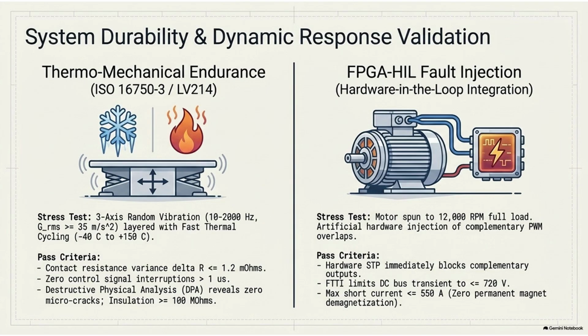While it's shaking, the table is sitting inside a thermal shock chamber. They rapidly cycle the ambient temperature from deep winter negative 40 degrees Celsius up to a scorching positive 150 degrees Celsius. Wow. And they leave it in this state, vibrating and thermally expanding while running high power through the circuits for over 500 solid hours. What exactly is that targeting? What fails under those conditions?